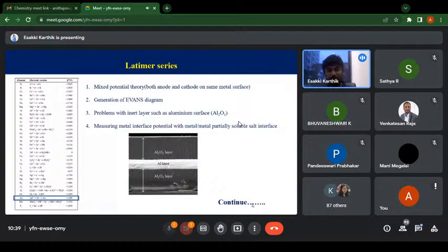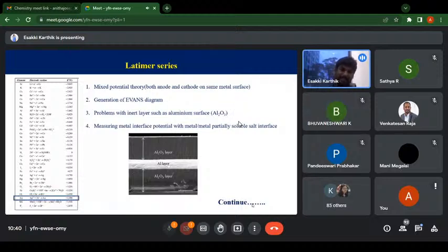Here I have mentioned, when you take aluminum paper that you buy commercially from the market, initially it may be very clean, very whitish in color. When you look at it very, very deeply, a thin, very pale whitish layer coating will be forming. That coating is nothing but the aluminum oxide layer. Because of this coating, oxygen cannot penetrate through the aluminum oxide layer. The aluminum oxide layer is highly inert, and it won't conduct electricity. Because of this reason, this Latimer series is sometimes not useful.